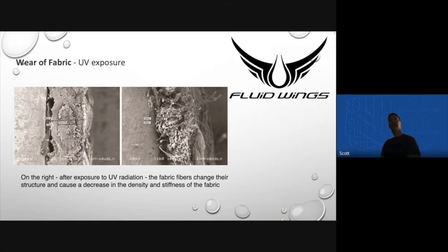So the one on the right is one that the UV has really worn out, and you can see it's not just that you lose coloration and stuff like that. You've actually lost portions of the fiber. You lost density and stiffness. So it's the actual fibers themselves that deteriorate. The matrix becomes less dense. You can almost feel it in an old fabric when you touch it. It feels lighter almost. And that's what's going on. It's almost like sublimation, like some of the fabric is cooking off. Some of the parts of the polymer are cooking off. It's not exactly what's happening, but it's a good analogy.